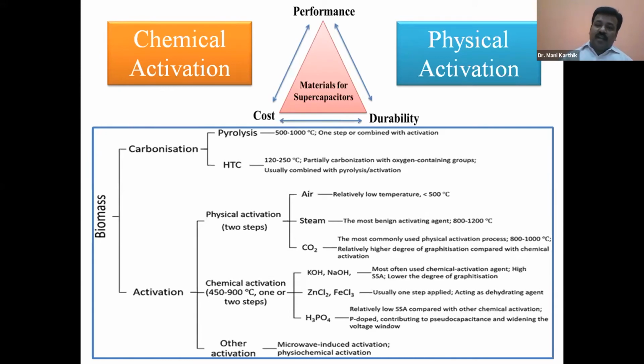For example, chemical activation, yield is very high, but after activation you need to remove the chemicals from the activated agent. For example, KOH. KOH is a very hazardous material, and after activation it's a porous material. The KOH or any chemicals are embedded inside the pores. It's not easy to remove the chemical species from the activated carbon. So we need plenty of water washing or neutralization, using acid to neutralize the carbon, in order to make neutral carbon with high purity. It's a very challenging task for chemical activation.